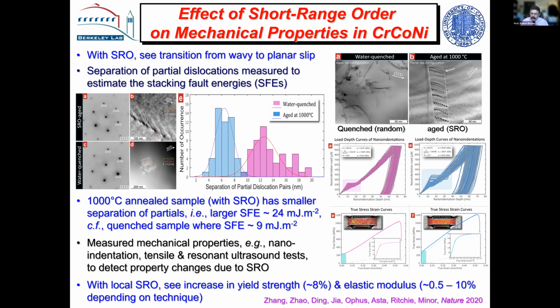So that's completely consistent with the predictions of DFT. When we look at nano indentation, these are nano indentation curves of the load versus the depth. What you're seeing here is the initial nucleation of dislocations, and it certainly is occurring at a lower level in the material which has random order compared to the material that has short range order. Now, we also measured a change in macroscale properties. We got a change in yield strength and we got a change in modulus, but that is still a bit of a controversy because you may not get an effect on the macroscale properties.